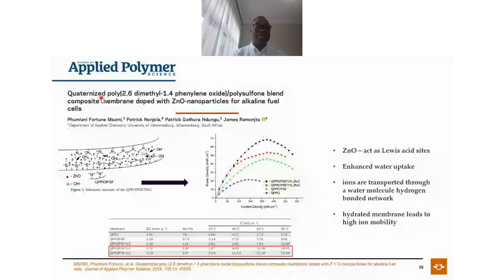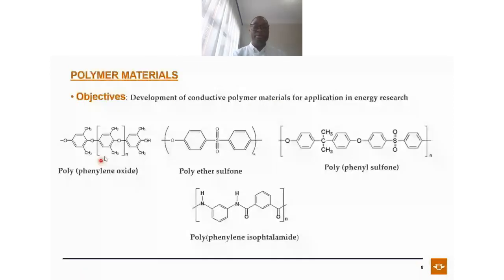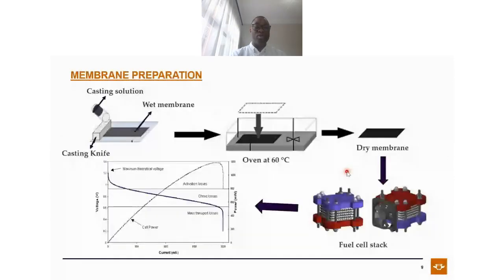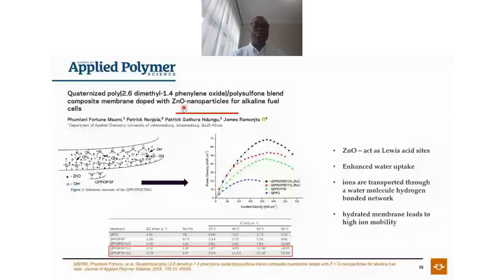Looking at this paper, which we published around 2018, we indicated that if you have a PPO membrane, this is the membrane that we're talking about, this one, which is PPO, this one is PES, and this is PPS. So we've taken this membrane, we've blended it with a polysulfone membrane, and we've also added what we call zinc oxide nanoparticles. We wanted to see what effect a metal oxide would have when we're doing our fuel cell.